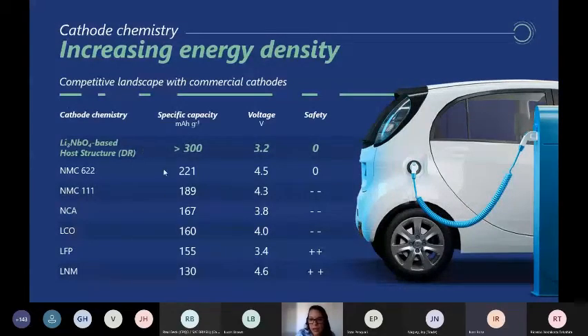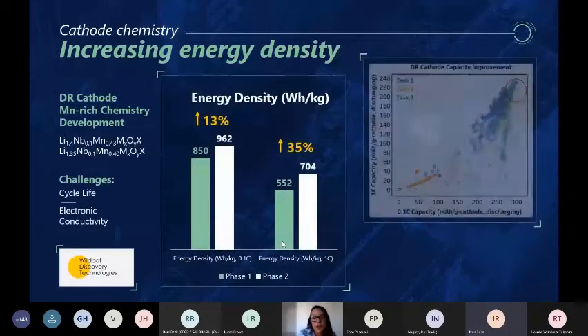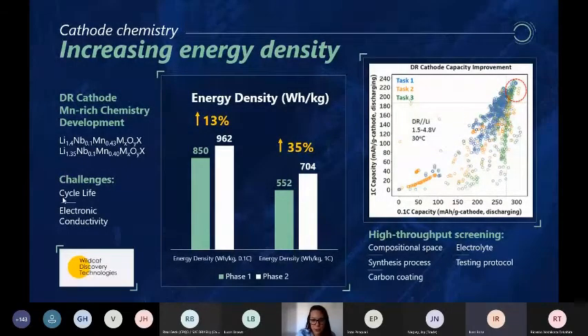Then you can see in the table that this study material presents a high specific capacity compared to the LNM and other commercial cathodes. Based on these quite interesting results, high throughput screening tests were performed in collaboration with Wildcat Discovery Technologies for studying two chemistries, disordered rock salt 1 and disordered rock salt 2 here, of cathodes. The first material showed an energy density improvement of 13%, and the second one, with lower lithium content, 35%, when you compare phase 1 and phase 2 of the project.